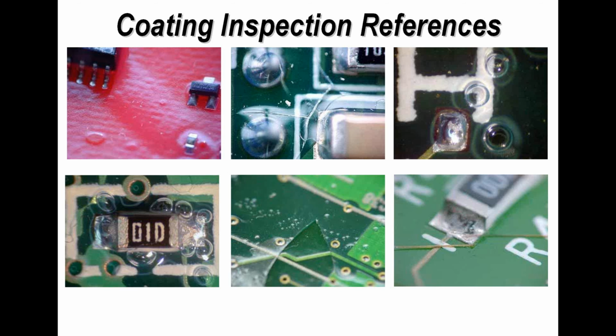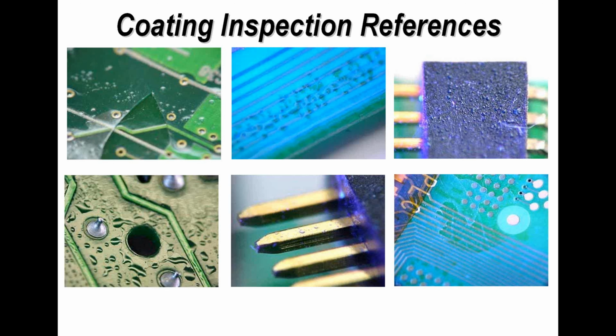Top left hand is a drainage mark, where the coating is draining down from a dip coating process. Center image, top row, shows cracking of a conformal coating. On the right hand top view we show fish eyes, and on the left bottom we show voids or bubbles in the coating. This is due to fast curing, probably. We show flaking or cracking of the coating in the bottom center view, and then foreign matter, foreign debris on the surface on the right bottom view. The point is, so everybody is clear what we're talking about when we're talking about defects or criteria for those defects. On the second group of slides, I've illustrated again some of the other issues highlighted.